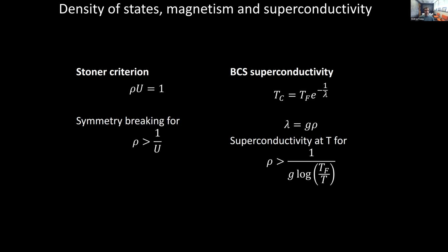So, for example, if you ask about magnetism in a metal, typically people talk about the Stoner criterion. The Stoner criterion basically says that when the density of states, which is rho here, times the Coulomb repulsion becomes about 1, in other words, if the density of states gets large enough for this to be 1, then that's when you expect symmetry breaking in magnetism. So it just gives you a sort of estimate for when magnetism would come about.